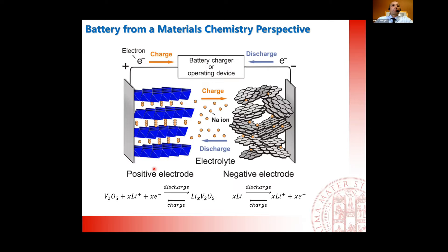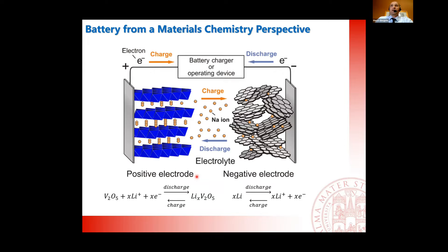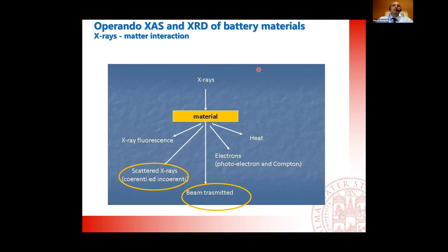There are fundamental questions that material scientists are interested in. First, for different ions, which metal has the electroactivity? One of the most performant materials now is NMC — a combination of oxides of nickel, manganese, and cobalt — and the question is which has the electroactivity. Another aspect is where does the charge go? We are interested in structural and electronic modifications upon the electrochemical reaction. Also, the electroactivity not only concerns the surface but also the bulk of the material, so we need advanced bulk techniques to disclose the structure-property relationship.